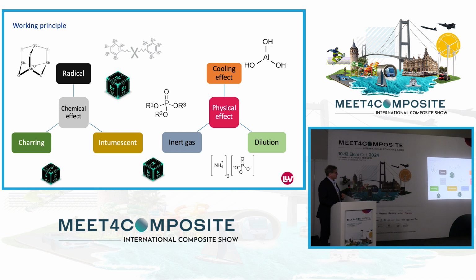Then you have the formation of inert gas and a dilution effect also. What you use for that are nitrogen and phosphorus materials. When we're talking about phosphorus materials, you have to be aware of regulations, because every molecule which has a strong effect also has a strong side effect. And lots of these materials are regulated under dual use or chemical weapons regulation. Sounds scary, but it isn't. It's a matter of documentation. That's all. We can help with that.